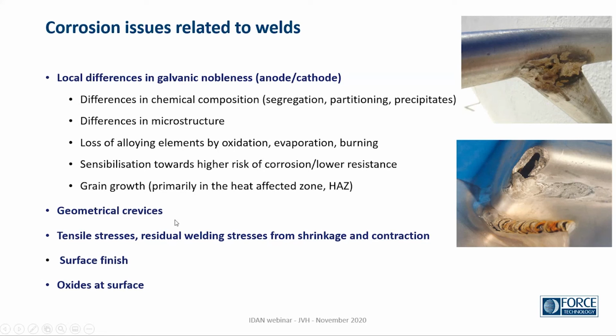And most materials depend on a passive layer for corrosion resistance, so they would be very sensitive to crevices. You can't keep the material passive in a crevice over time. It will lose the passive layer in the crevice. And also, as we have talked about before, tensile stresses, residual welding stresses can cause problems. And the surface finish in and around a weld would also affect the corrosion resistance. Oxides on the surface have an effect. And of course, the example up here in the corner, poor workmanship would also mean that this is more sensitive to corrosion. Any deposits, contamination would stick to this weld very easily and might cause problems.